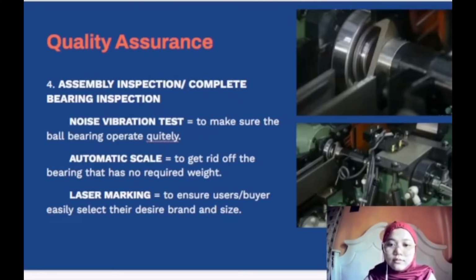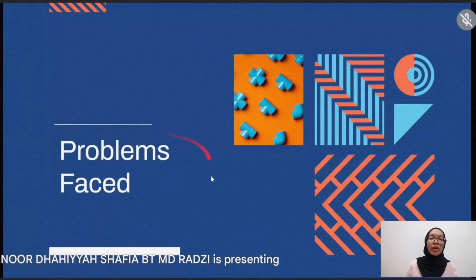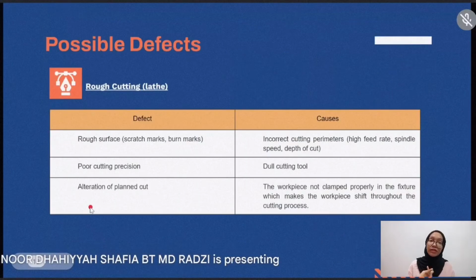Thank you. Next, we will talk about problems that we face during the manufacturing process, such as possible defects and other problems. In rough cutting, the possible defects include rough surface, which are scratch marks and burn marks, caused by incorrect cutting parameters such as high feed rate, high spindle speed, and large depth of cut. Poor cutting precision is caused by a dull cutting tool, while alteration of plane cut happens when the workpiece is not clamped properly in the fixture.